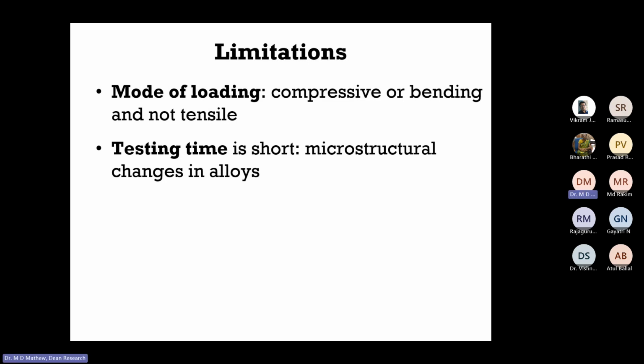And since these are all quick tests, testing time is short. But when it comes to alloys, which can undergo microstructural changes over a period of time when exposed to high temperature, we'll be able to capture that effect in a standard test, where, for example, a creep test may go for hundreds and thousands of hours. But since these tests are short duration tests, we may not be able to capture the changes in the property of the material that occurs as a result of microstructural changes.